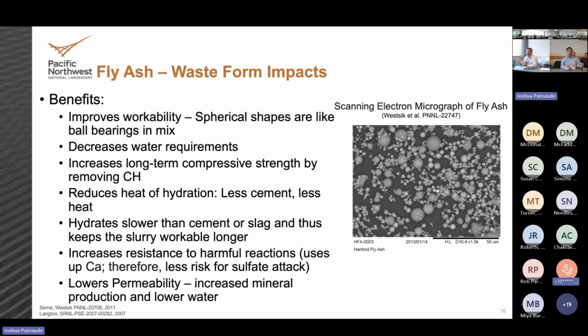And the introduction of fly ash is actually crucial to the production of the saltstone waste form at the Savannah River site, because they take their waste, mix it in a central facility, and then they have to pump it out to the large disposal units. The introduction of about 45% fly ash in their mixture actually helps with sustaining flow of the slurry through that line and into the large vault, specifically because of these properties. So we use it quite a lot because it does, again, give us good control of our rheological properties. Next slide.